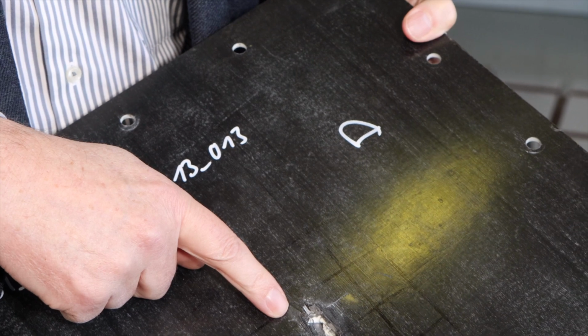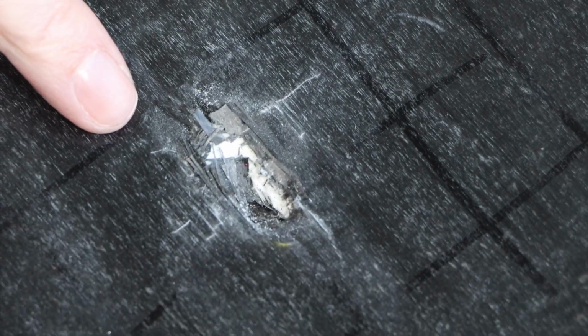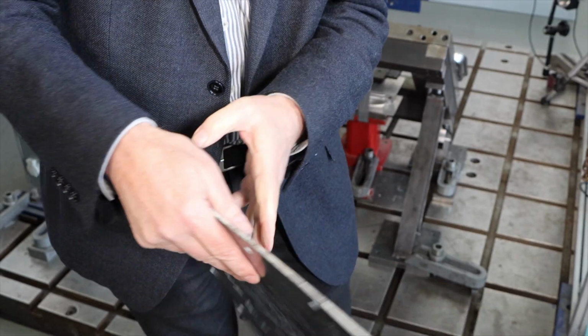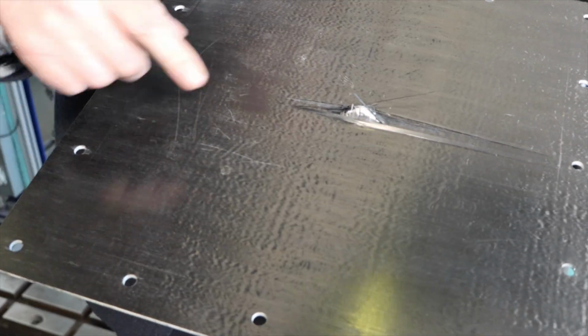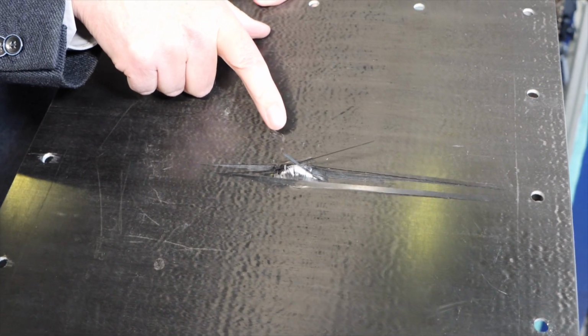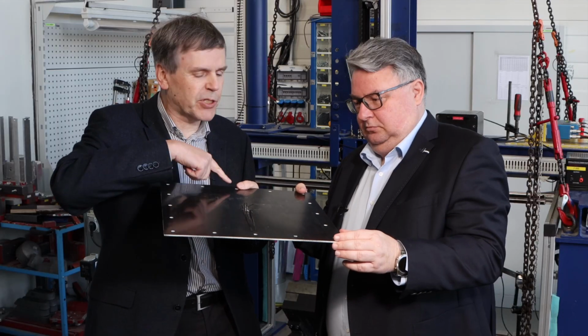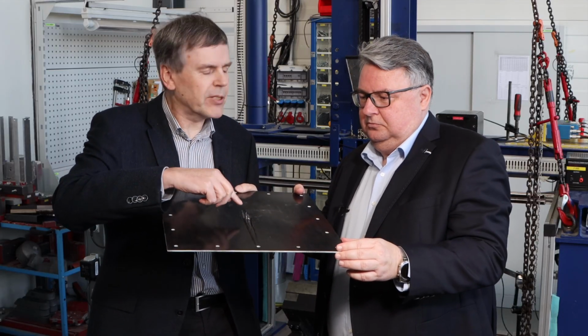So we are back. That was really a big, loud bang. I'm sure you have not felt it in the video, but it was impressive. Very fast though, but very, very impressive. So Warden, what is your conclusion on this test? I would say this is quite a nice result. You see there is some damage on the entry side. It's quite limited. If you look at the back side, then you can see that there is more spreading of the damage. This is actually quite a good thing, that this UD material spreads the damage to a larger area. So the penetration is not very deep.